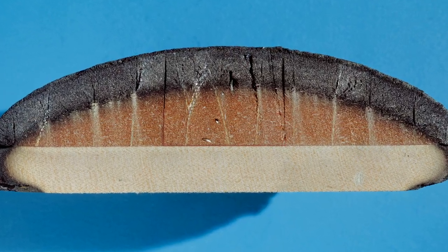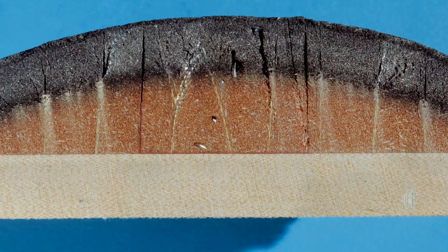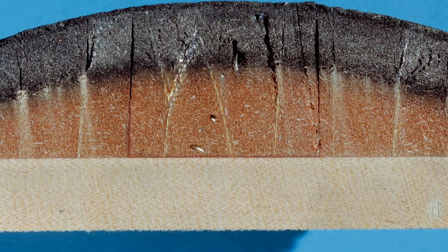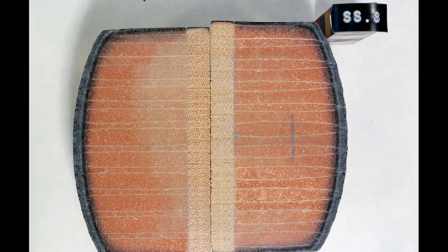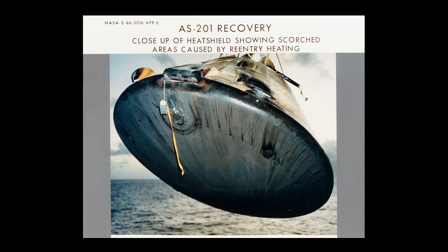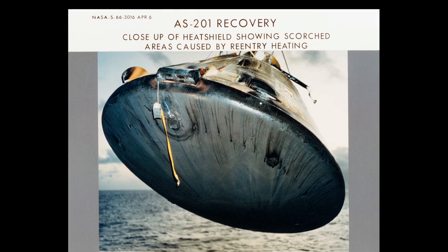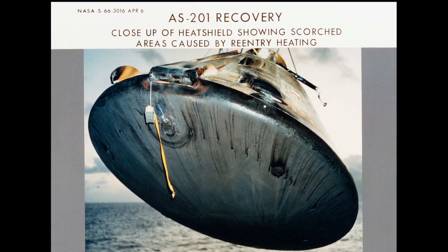Absolutely. The Apollo material, because of the arc jet testing, went from a high density material of around 60 pounds per cubic foot all the way down to around 32 pounds per cubic foot by the addition of some fillers, we called them, within the material. And we still got really good performance. We got good temperature performance, good insulation performance, and the good surface performance that we wanted from the ablator itself. So absolutely, you can test a material with various compositions and make good judgments on how that composition changes that material under these conditions of pressure and temperature.